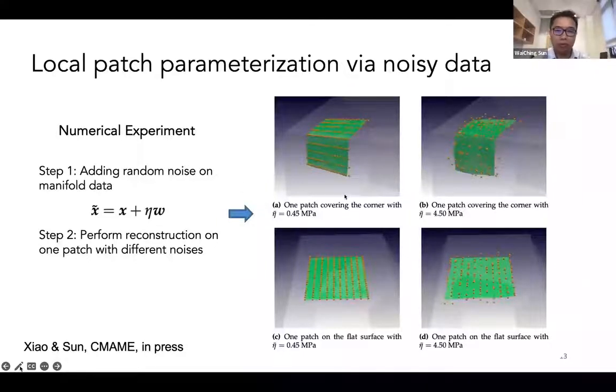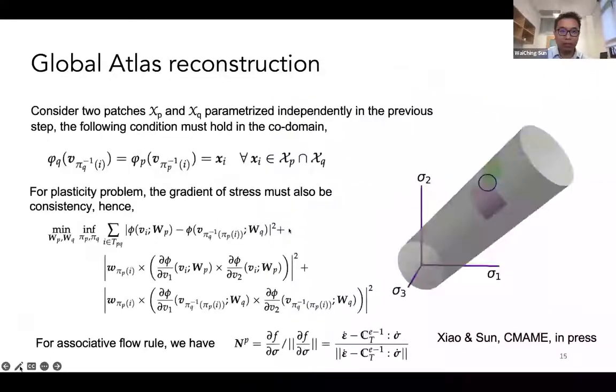We put it into the Drucker-Prager yield surface, and we can see that if I purposely introduce noise in the material, which in real-life experiments would very well happen, we can use this Sinkhorn regularization term to help us obtain a good behavior that is stable. For an associative flow rule, the yield surface gives the plastic flow, meaning that the gradient of this yield surface is related to the growth of the plastic deformation. So if we can get a stable direction, this is very important to help us trigger the right plastic strain that is triggered beyond the yielding. And here we can see that there's a good property in the sense that it filters the noise, but it also maintains the sharp features of the yield surface that we play with in that numerical experiment.